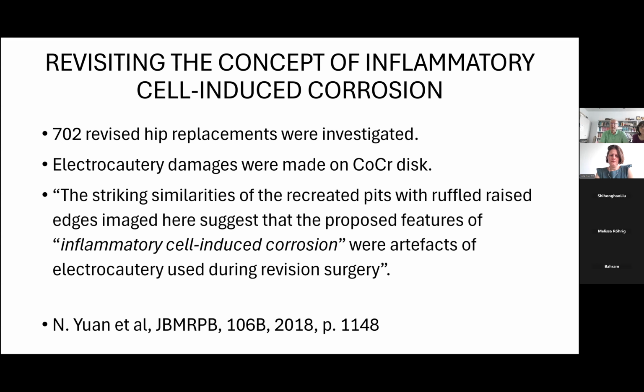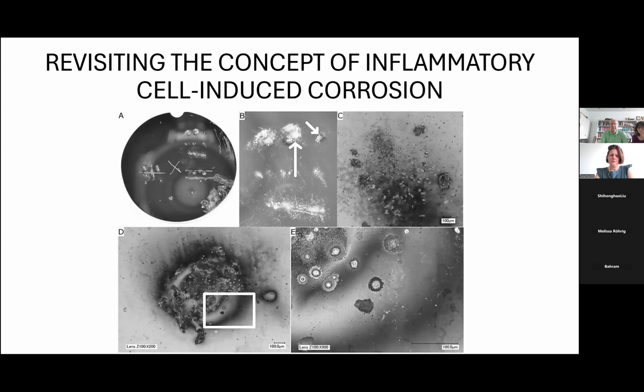And here they were able to show that what the other paper was saying, inflammatory cell-induced corrosion, was actually artifacts due to the electrocautery during revision. And here you see, for example, from the second paper, exactly the same kind of surfaces, but it was due here to the contact between the electrocautery and the metal. It is maybe the third example, but you can see something very interesting: a statement about corrosion in the medtech or in orthopedics, which is absolutely wrong.